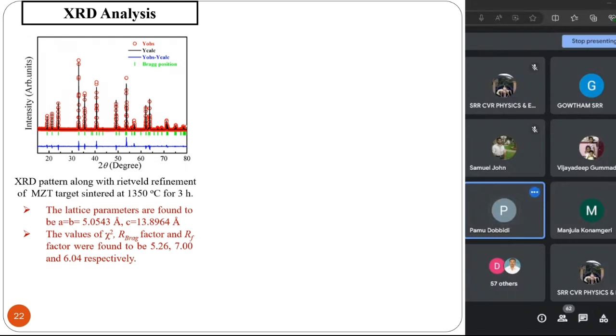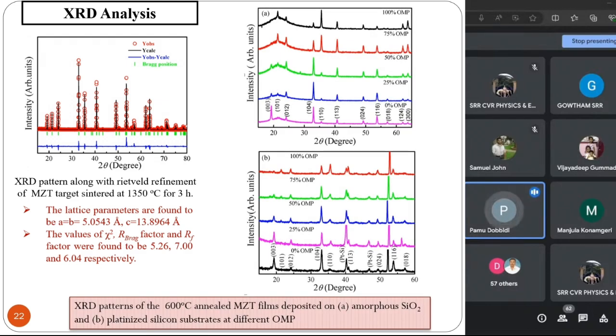Can you enter? Yeah. So now what we did is that we made thin films on silicon, platinized silicon substrate and quartz substrate. You may ask, what is the importance of platinized silicon? Because we want to make a thin film capacitor. When I make a thin film capacitor, what is required? I need a bottom electrode and in between my magnesium titanate thin film and top electrode. So for the bottom electrode we chose platinum.